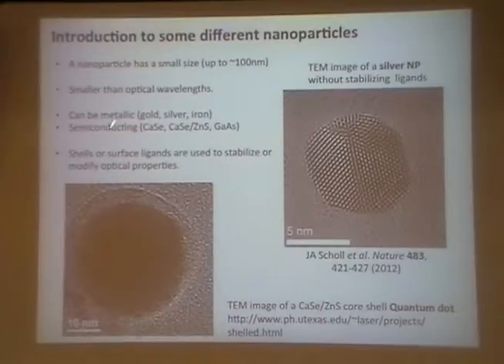Okay, so basically, a nanoparticle has a very small size, less than 100 nanometers, I think, you can qualify. Most of the things that we're looking at are just a few nanometers, say 5 to 10 nanometers in size. So we're getting down to particles that are of the order of the size of the liquid crystal molecule, but not so small that they're going to ignore the liquid crystal. If you went down to less than a nanometer, they may not interact with the director. But they're definitely very much smaller than optical wavelengths. You're not going to be able to see them, but we can see optical effects that result from their arrangement or assembly, potentially. It can be metallic, so there's lots of work that's gone on in gold particles and silver particles, making different shapes and functional structures that can be put into liquid crystal.